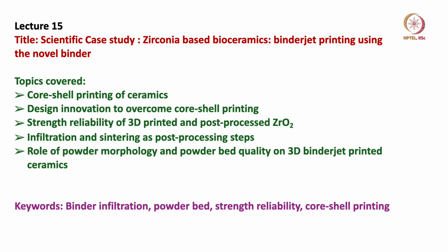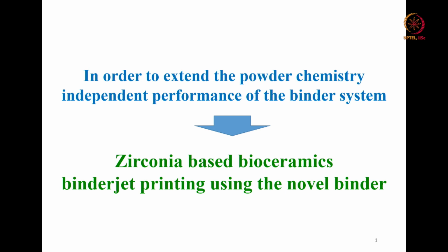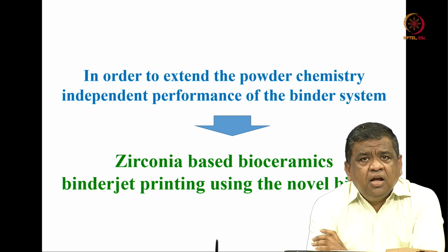So, in the last lecture we have seen how the in situ polymerizable ink was used to binder jet 3D print the Ti6Al4V materials. So, we wanted to explore whether a similar ink formulation can be equally effective for binder jet 3D printing of ceramic based materials. One of the ceramics that our research group has investigated in the past, and that I personally have investigated during my PhD thesis, is the zirconia based ceramics. So, consequently, our aim was to see whether zirconia can be 3D printed using that in situ polymerizable ink.